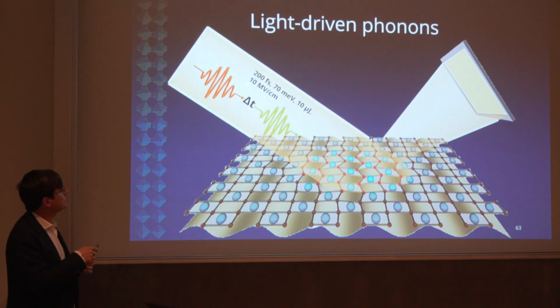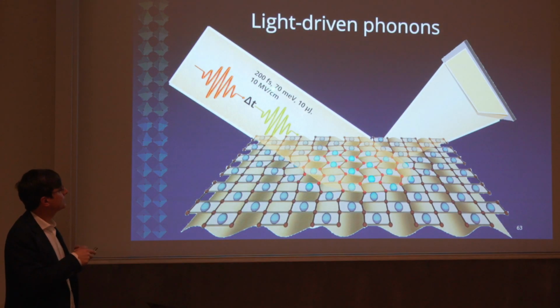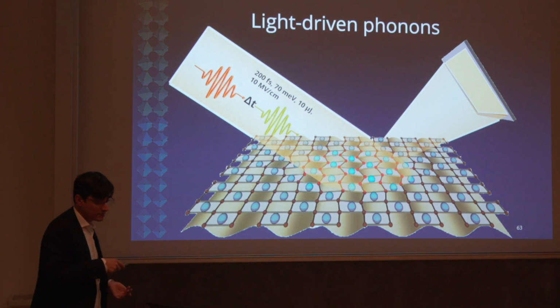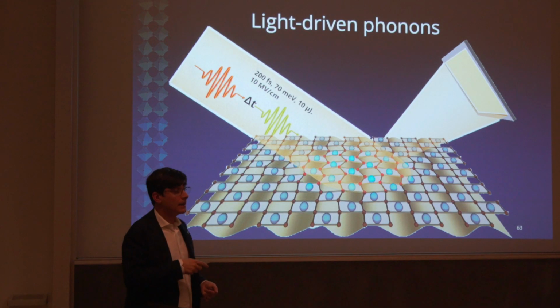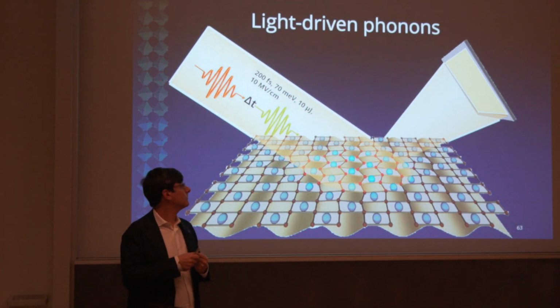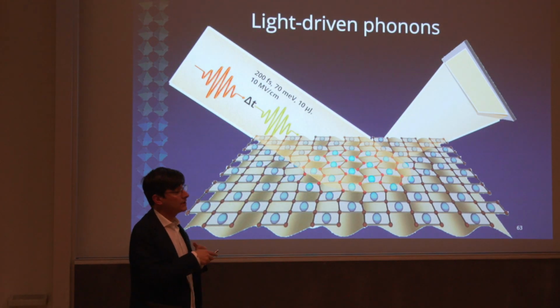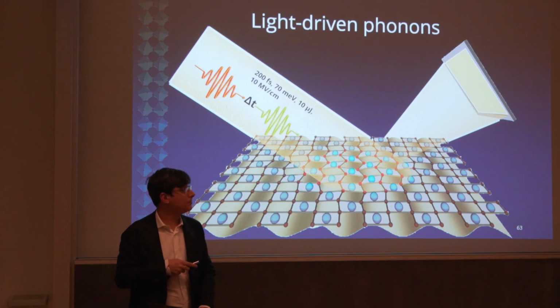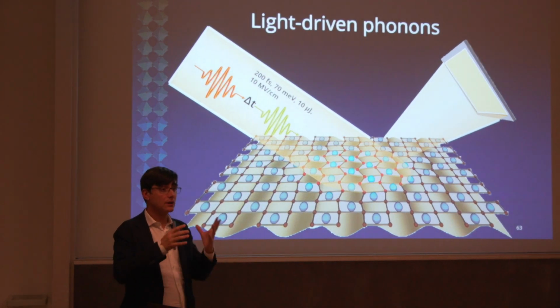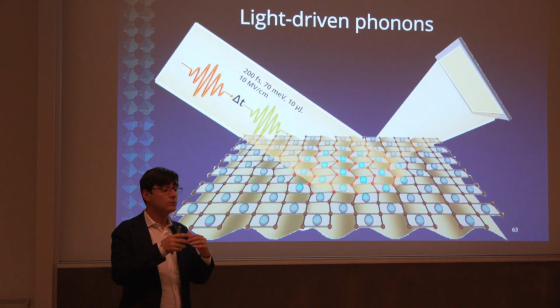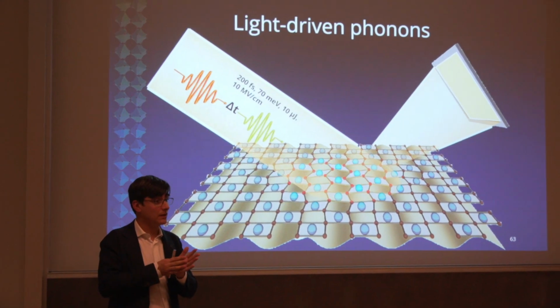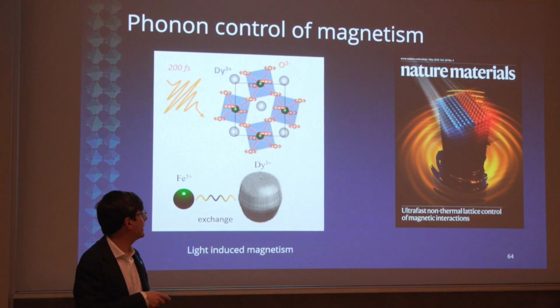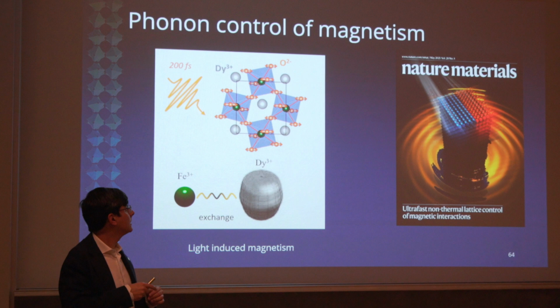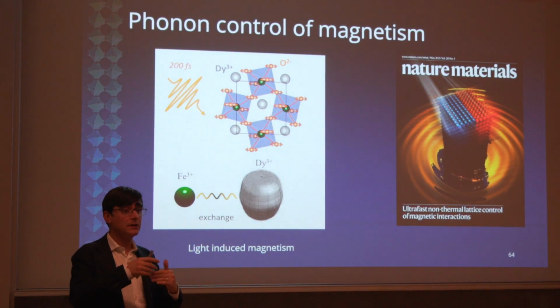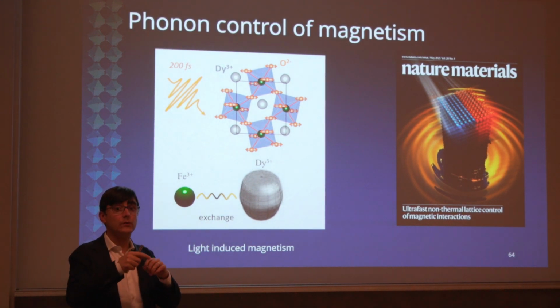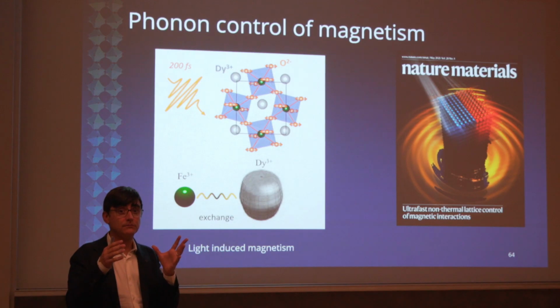All right, and so this is the whole story of light-driven phonons. By using mid-infrared laser pulses, we can excite materials out of equilibrium, and if we do it with a strong enough electric field carried by your excitation pulse, you can generate a crystal structure out of equilibrium that would not exist in the material otherwise. So you can create atomic arrangements that live for a certain amount of time in an out of equilibrium state where your materials start to have new properties.